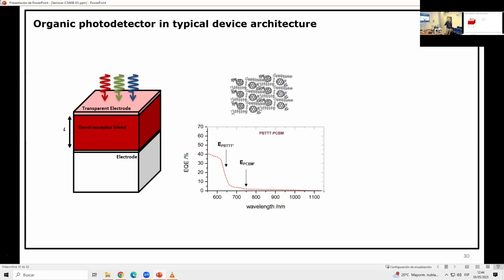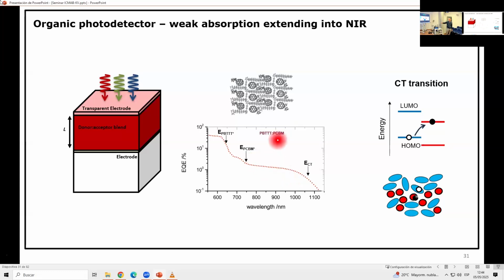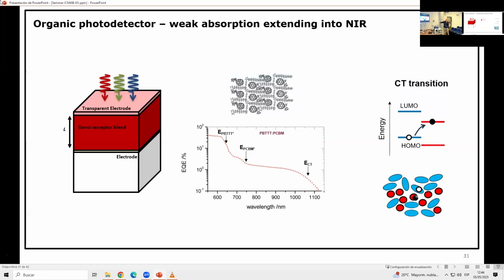So actually, if you look deeper at that little amount of absorption which we had here, and you put the axis on a logarithmic scale, you see there is absorption. And we've been looking for so many ways to make materials which can absorb at 1,000 nanometer or longer. And actually, by just blending those 2 materials, you make a weak absorber, but it does absorb at 1,000 nanometers, but only 1%. Where does this come from? All this extra absorption at this long tail here?